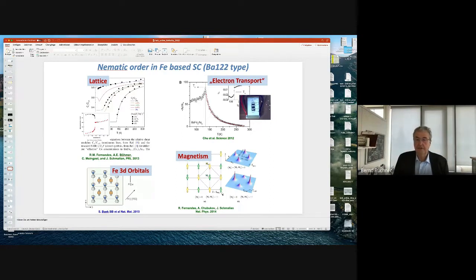On the other hand, it's also well established that the magnetic order, which you have at low temperatures, so this antiferromagnetic order, is stripe-like. So you have this ferromagnetic stripe and then the next stripe pointing in a different direction. So this apparently also breaks C4 symmetry just from the magnetic structure. And a lot of people argue that indeed this magnetic instability, this spin density wave instability, drives the system from a tetragonal to an orthorhombic state, drives the structural phase transition. So is it purely orbital? This is indicated by the fact that it also occurs in systems which do not have long-range order. Or is it mainly spin-driven? And this is, for example, barium 122, where the phase transitions come simultaneously. There it seems to be really a single instability. Maybe it's still debated, and probably both aspects play a role.